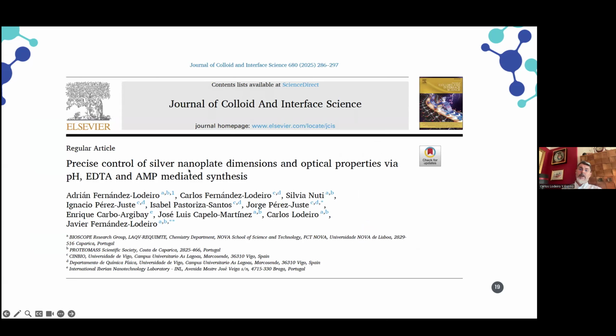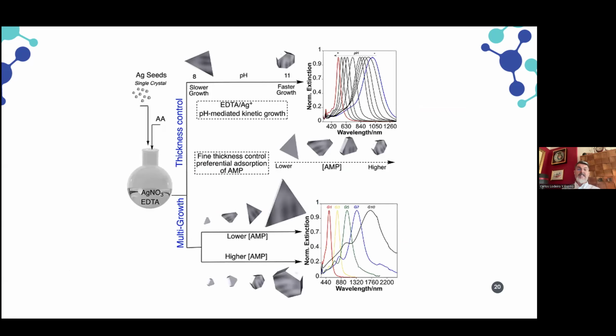And this paper I show you here was published very recently, in which we use adenosine monophosphate, AMP, which also works with ADP and ATP, and is a biological molecule, very compatible with the final material. In the presence of EDTA, we can play with the pH, and we can, for example, produce anisotropic materials in a way that controls the dimension of the materials. In this case, we produce nanoplates. These triangle nanoparticles can also grow in thickness and in length.